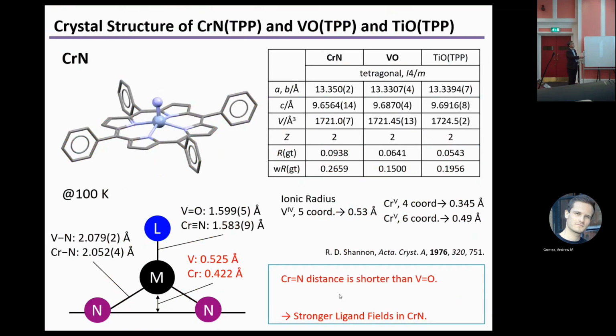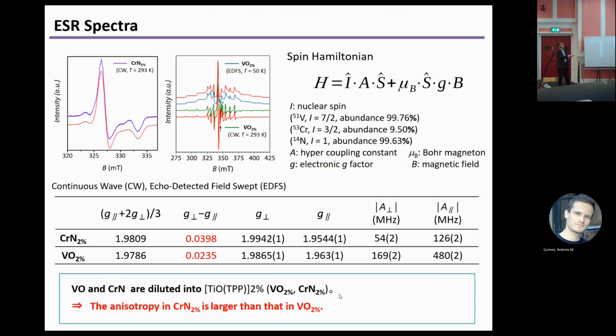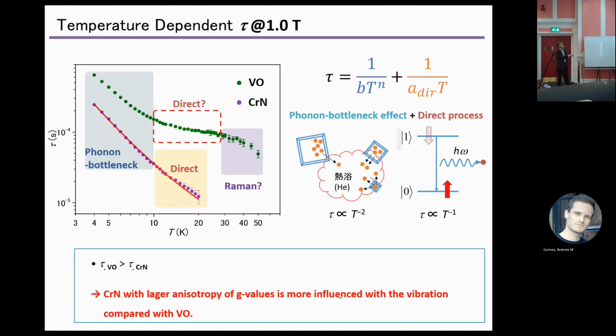So this is a crystal structure. From the square planar, chromium and also vanadium are distorted. So this is an EPR spectrum. You can see chromium nitride, g anisotropy is 0.0398, but oxovanadium anisotropy is 0.0235. So oxovanadium has the smaller anisotropy of g value. So then this is the result, relaxation time. Chromium nitride shows a faster relaxation time. On the other hand, oxovanadium shows a longer lifetime because of the smaller g anisotropy of oxovanadium.